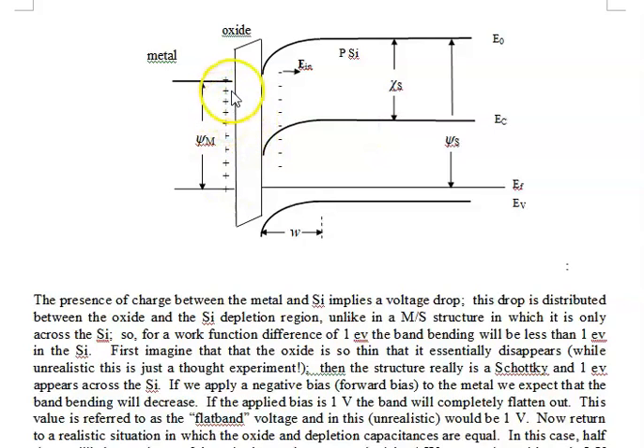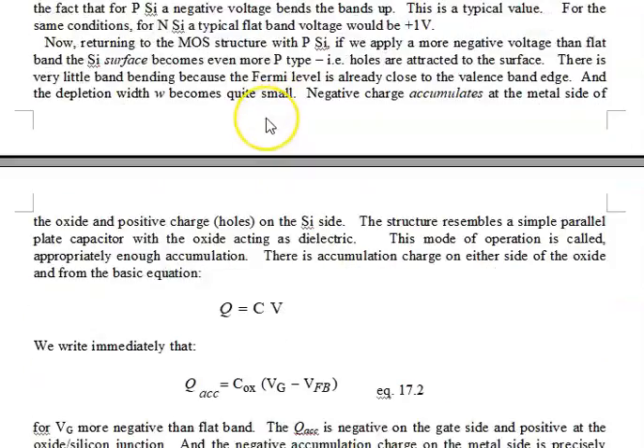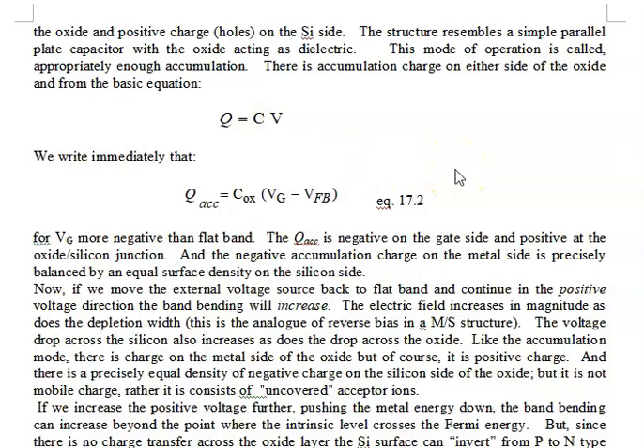And then I keep going, so I have a minus charge on the metal, and that attracts holes in the silicon, and the bands, instead of bending down, they flattened out. We applied a negative voltage of minus 1 volt. They became flat. I applied, say, 1.2, 1.3 volts. So instead of bending down, they start bending up. It becomes more P at the silicon, and then basically all I have is a capacitor. So that's where we're going to end.